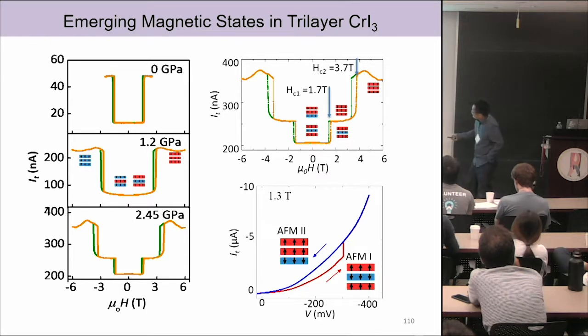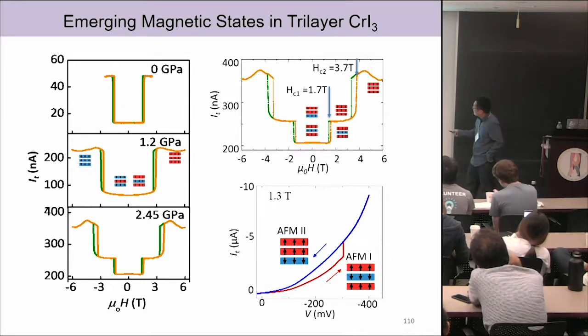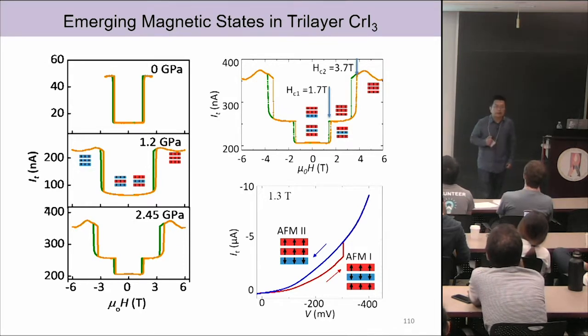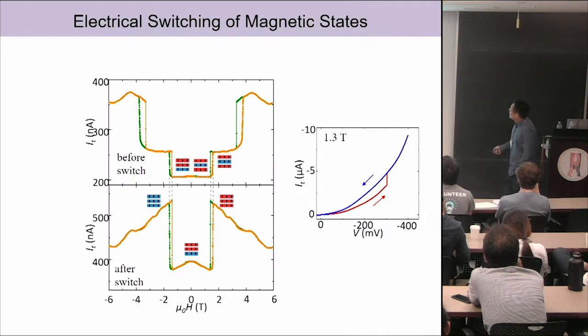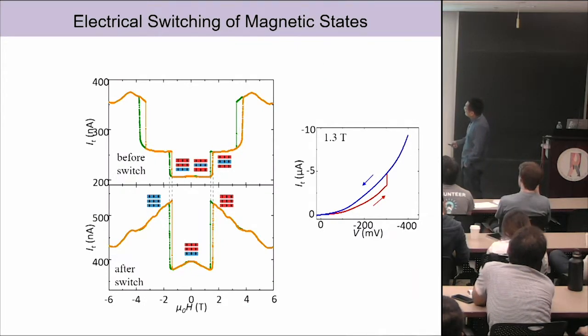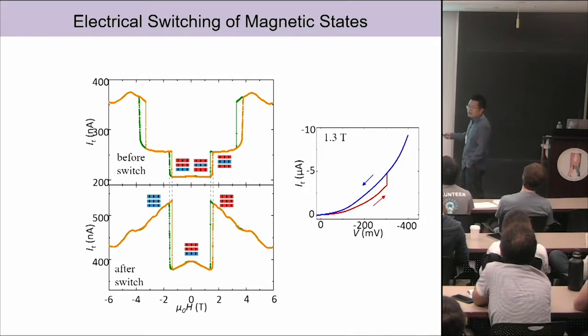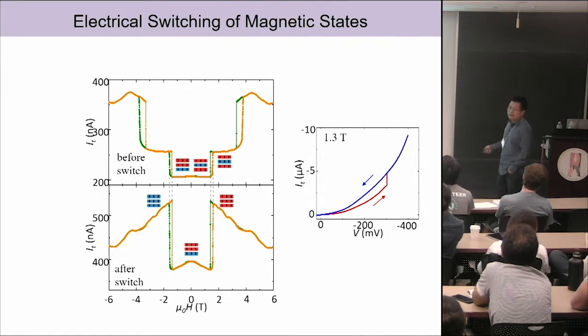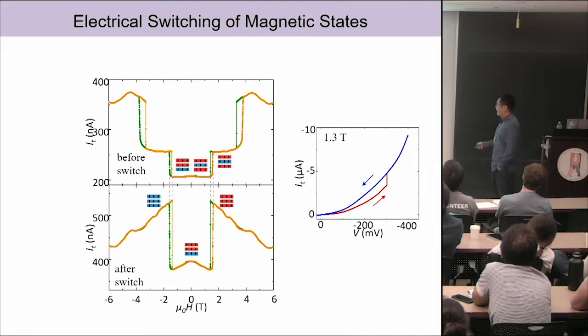So what we did is we just scan the bias, and then we see a jump. Then we scan the bias back. You get this blue curve, but it doesn't go back to the red curve. So this transition happens where electric current switches the system from antiferromagnetic state 1 into antiferromagnetic state 2. So how do I know that? Well, very simple. Now I can scan the magnetic field again to measure the tunneling current. The top one is before the switching happened, the bottom is after the state switching. What you see is that after state switching, only the lower field transition stays. The top one has vanished. So what that means is now all the states I have are in antiferromagnetic state 2.